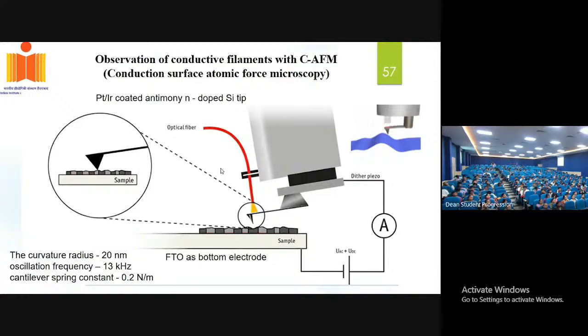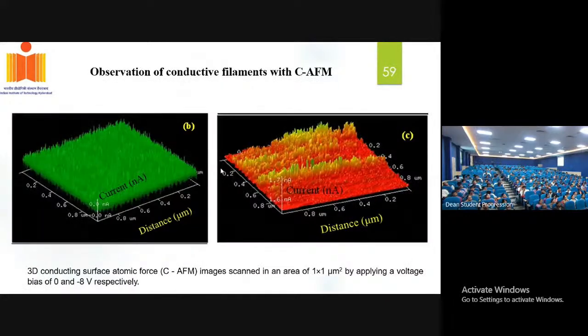Now over here, we try to replace the atomic force microscopy with conducting atomic force microscopy so that you can map the conducting channels in the device. So these are the images that we have obtained. This is the CAFM image, conducting atomic force microscope image, and this is the image when you apply the voltage of 0 volt, and this is the image when you apply the voltage of minus 8 volt. If you see the difference between these two images, we don't see any conducting channels in the first image. That means that when you don't apply any voltage, there are no channels, and when you apply the voltage, we do see conducting channels. So these conducting channels basically represent the oxygen defect. I have shown you one image where the top electrode and the bottom electrode are connected by conducting channels through oxygen defects. So these conducting channels are because of the oxygen defects in the device. So they are making channels, and we were able to confirm these channels using conducting atomic force microscopy imaging.